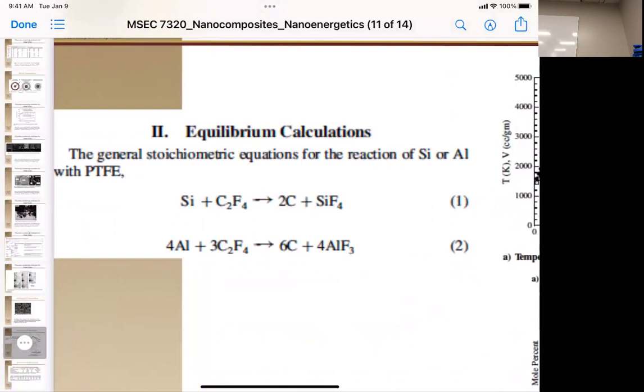the energy output for the transfer of the fluorine to the silicon or the fluorine to the aluminum, we actually have the silicon wanting to use up 4 equivalents of fluorine. The aluminum uses 3 equivalents of fluorine. But if we look at the stoichiometry here, that means for every 4 aluminums, we have to have 3 Teflons, which gives us 6 equivalents of carbon and only 4 of these, where here, this is a more thermodynamically better reaction. And your silicon tetrafluoride is a gas at room temperature.